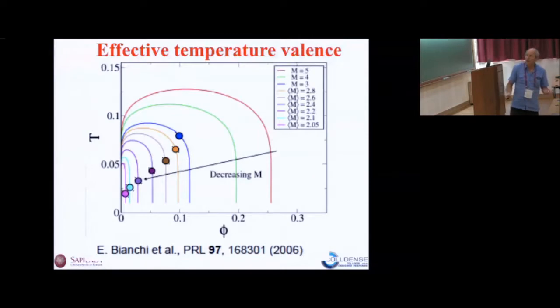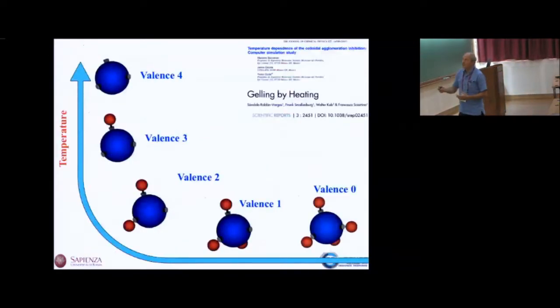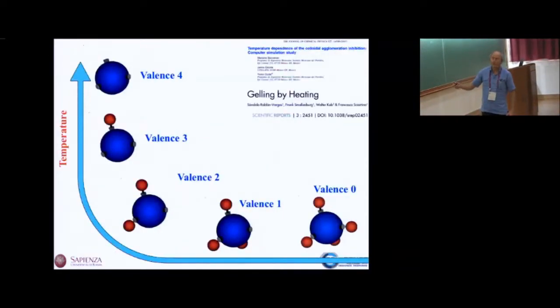A particle which changes valence by itself and goes, let's say, from 4 to 1 or to 0. I can do this. I can say, okay, I have my particle with valence 4, and then I can transform this particle with valence 4 into a particle with valence 3 just by attaching another particle on it, capping one of the bonds, right? And then I can transform this particle, which is valence 3, into a particle with valence 2 by capping 2 bonds. I can transform this into a particle with valence 1 by capping 3 bonds, and then I can even transform this into a particle with valence 0 by capping all the bonds.